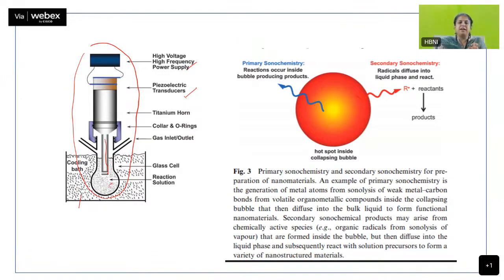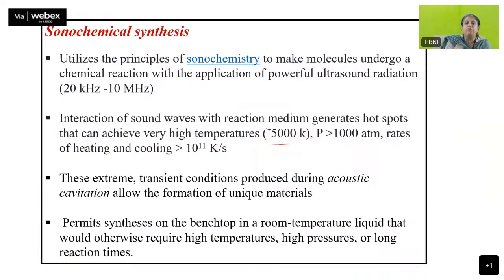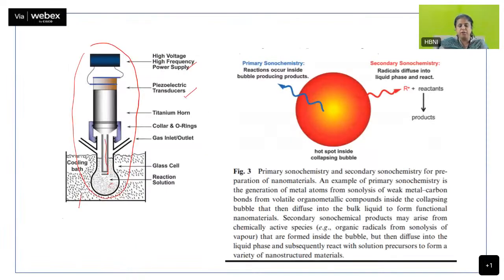Why is the reaction possible in these acoustic cavities? Because for a very small duration of time, we can get high temperature of the order of 5000 Kelvin and pressure greater than 1000 atmospheres. And because it persists for a very, very small duration of time, the heating and cooling rates are very fast. Because of this, the reaction happens. You can get metastable product. And the beauty is, outside the temperature is ambient, right? So it permits synthesis on a bench top in room temperature liquid, which would otherwise require very high temperature, high pressure, or longer reaction duration.